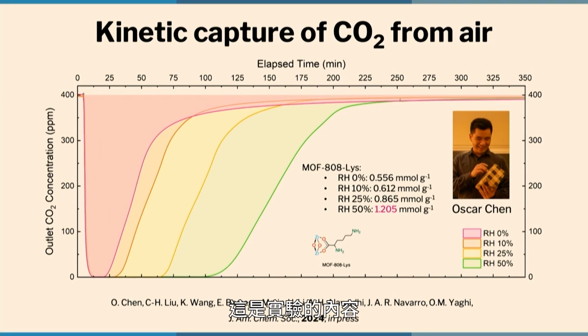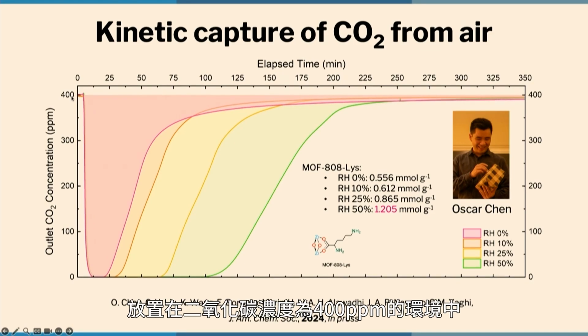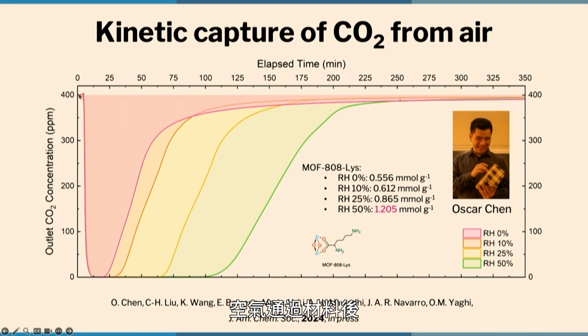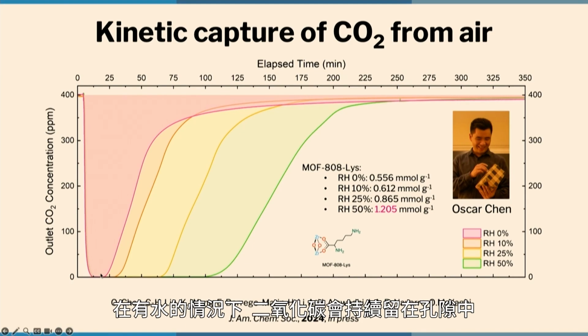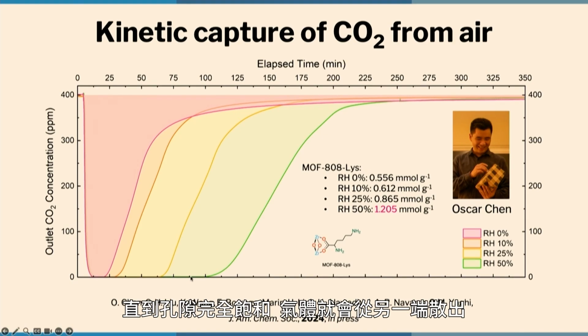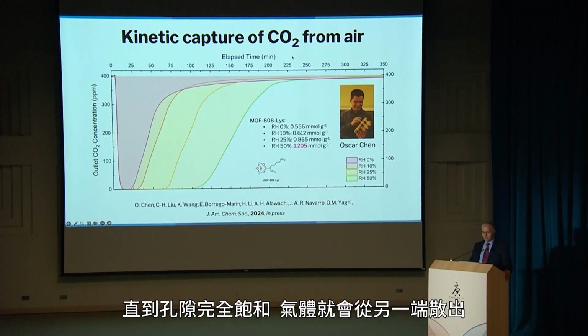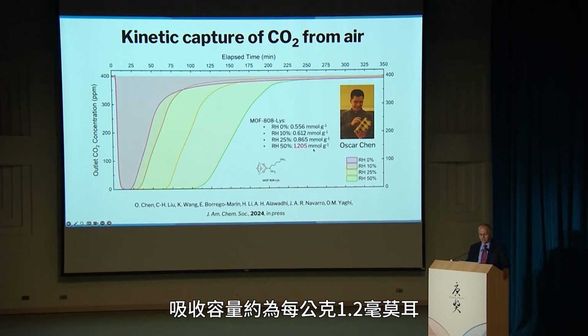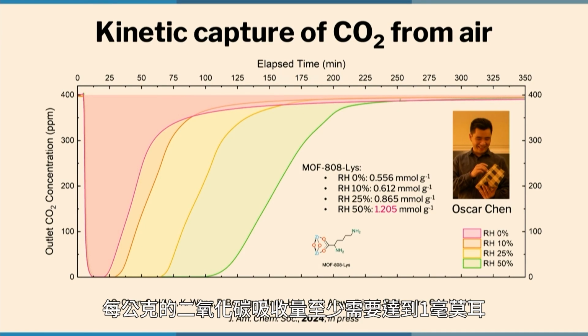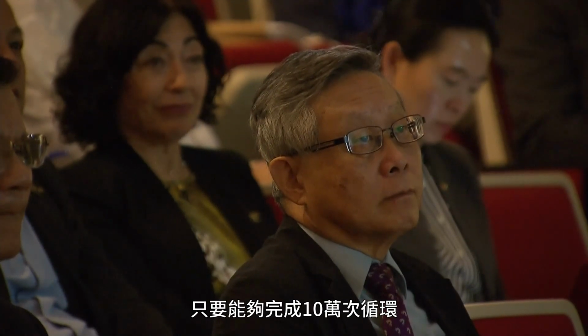Okay, so here's the experiment. A tube of MOF is exposed to 400 ppm of CO2, and as soon as it hits the material, the amount of CO2 coming out goes down to 0. It captures the CO2, absolutely beautiful. There's nothing like it. And in the presence of humidity, it stays in the pore until the pores are completely saturated and then breaks through on the other side. The capacity is about 1.2 millimole per gram. For a commercializable material, you need at least 1 millimole of CO2 per gram. We are over that. And you need the material to cycle 100,000 cycles. Regardless of the cost of the material, if it can cycle 100,000 cycles, and it has a capacity of 1 millimole per gram, it's commercializable.